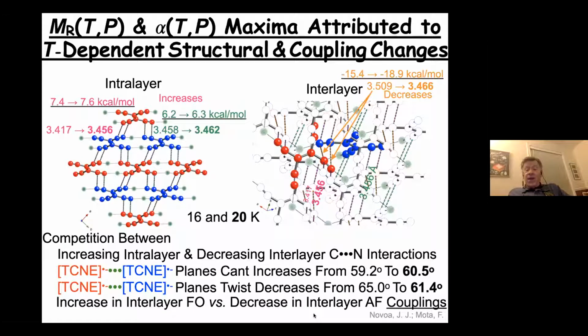And preliminary magnetic couplings calculated by Novoa's group show that the intra-layer coupling over here is actually ferromagnetic, and it's slightly more ferromagnetic, going from 16 Kelvin to 20 Kelvin, whereas the interlayer coupling is anti-ferromagnetic and goes from minus 15.4 to minus 18.9. So there's some structural changes leading to coupling changes, and some are ferromagnetic and some are anti-ferromagnetic. And this plays a complicated interplay between them, which likely leads to the change in the canting angle as a function of temperature.